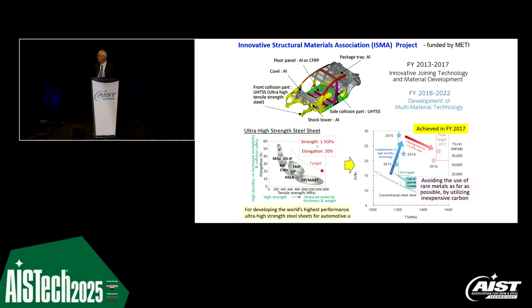Thank you again. Okay. So I think part of the work and research is still going on after the ISMA project, and also steel company people are working on such issues. For sheet steel, I think induction heating and online heat treatment is rather easy compared with thick plate steels. So that can be done, using the manganese heterogeneity in sheet steel applications. For thick plate, that's for high nickel alloy. Of course, you can again use reversion, where the morphology dictates the nickel partitioning too. So that is a very important issue for both plate and sheet steel applications.